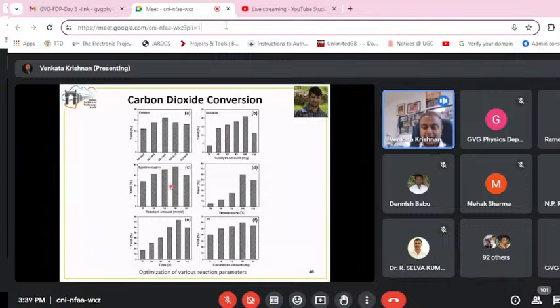We optimized the reactant amount, wherein epichlorohydrin was used as a model reactant, and we optimized it to about 20 millimole of this reactant. Then we optimized the temperature, and again we found 100 degrees C is the optimal temperature.